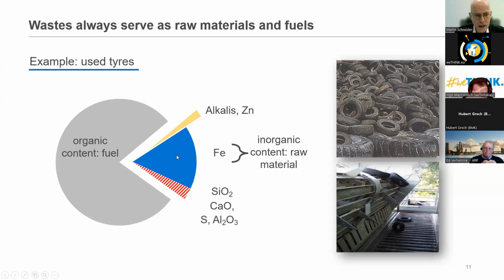And many raw materials at cement plants are poor in iron, and iron has to be added. Therefore it's a win-win situation when, for example, tires are used, which have a high content of iron in the steel belt around the tire. It's a win-win because all the material is used for clinker formation. And this is on the other side, and Hubert Brecht has underlined this, it's a need, because all of the materials are kept in the clinker. They stay there. There's no extra waste stream to be generated.